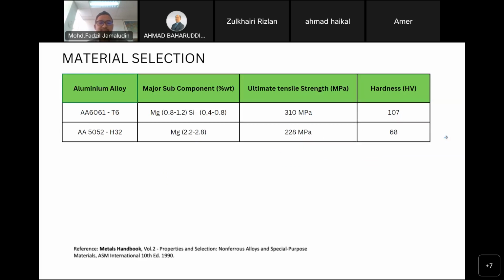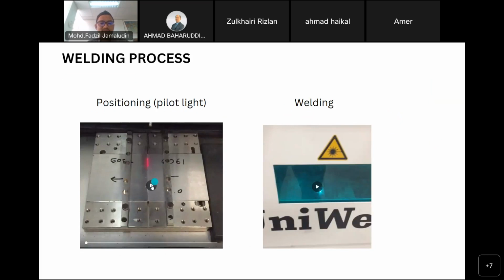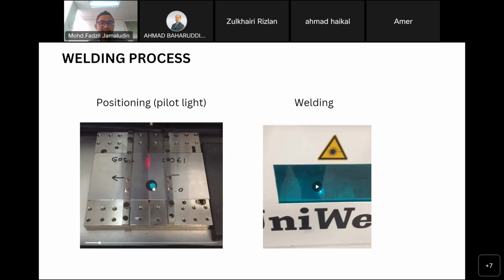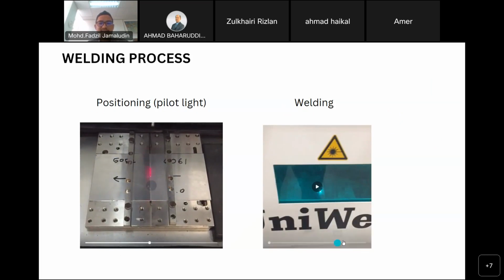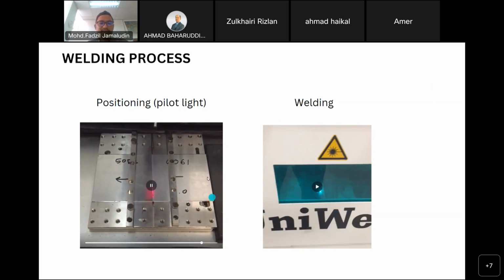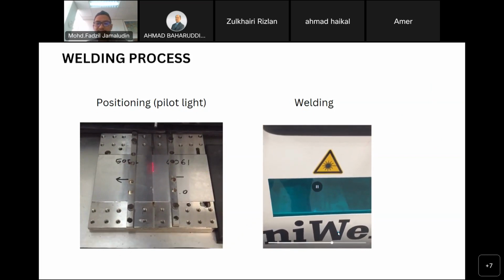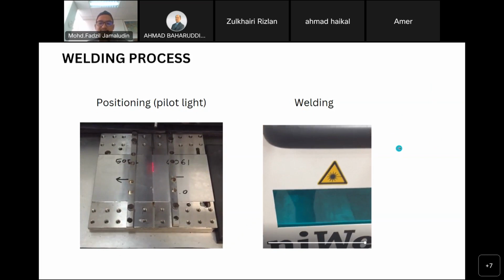And the material section, this is from the handbook, and then we actually did EDS to see what are the components in the materials. And just to show you, this is the configuration of the plates that we have used. One plate is here, it's another plate, and this is the pilot light. So this is where we are welding. And then when we actually weld it, this is a very fast weld. It takes less than 10 seconds to do the 10 mm weld.